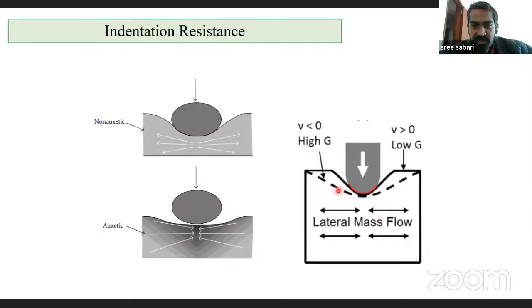So here you can see that if you are having a conventional material, this is not B, this is nu, which represents the Poisson ratio. So the Poisson ratio is greater than 0, which is a positive Poisson ratio. When you are having a positive Poisson ratio, you will have lower shear resistance, which was explained in the previous slide. And when you are having a negative Poisson ratio, you will have a higher shear resistance. So here you have a lower shear resistance, which allows larger indentation. Whereas when you are having a negative Poisson ratio, you have a lower indentation, whereas the area is bigger.